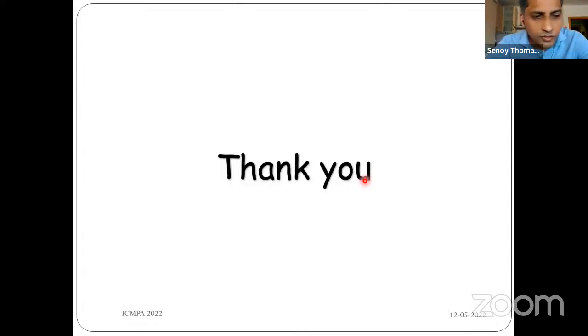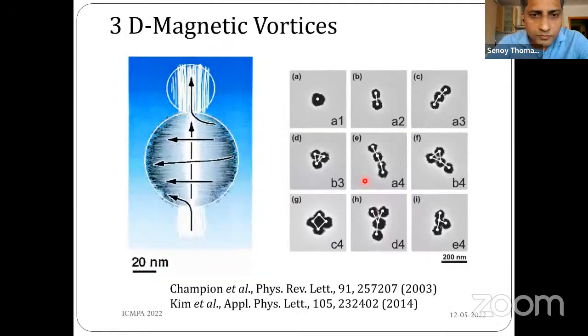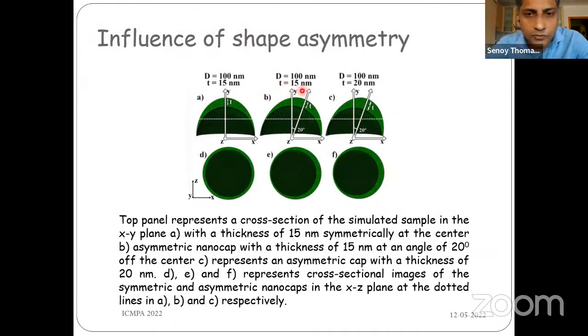Actually, our focus in this particular work was basically on these cap structures. So basically, from the experimental point of view, our aim was to do some oblique angle deposition so that one could tune the shape anisotropy associated with the system. And one problem which we really face is that the vortex nucleation is random. So if you look at the MFM image, at one point, the core is pointing up and at another point it is down. So somehow by tuning the shape, is there any possibility to collectively nucleate the vortex system or to control the chirality and the polarity? So this was the experimental motivation.